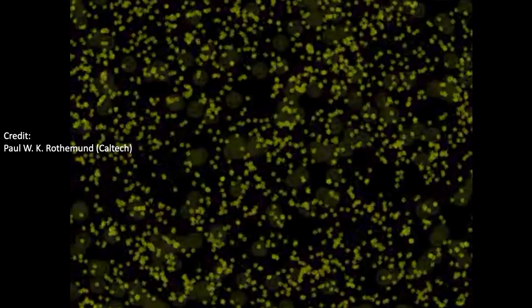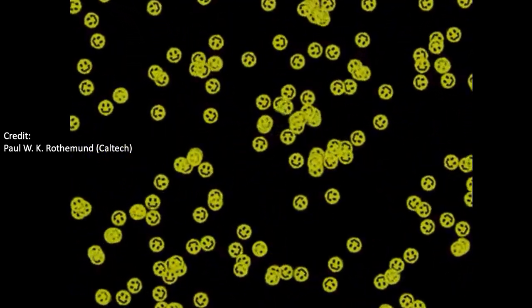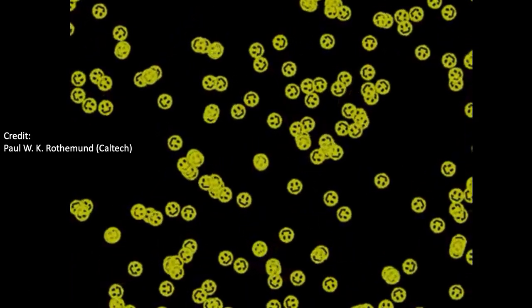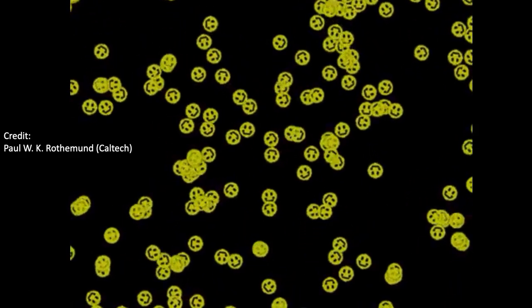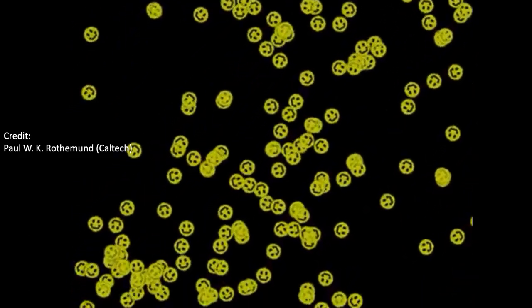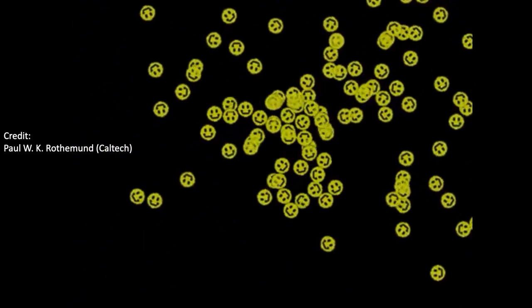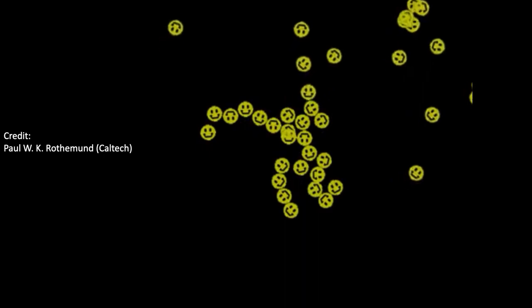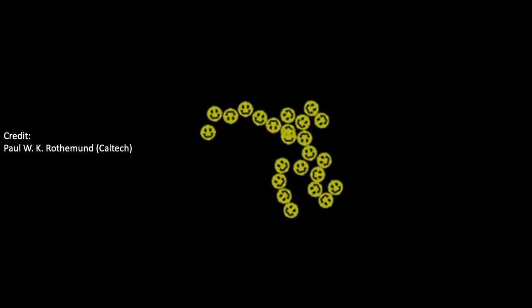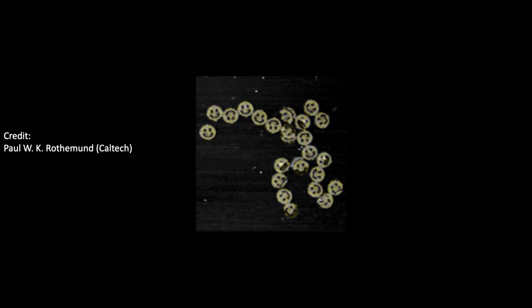What I meant by a parallel fashion is that many of these folded DNA nanoarchitectures can be obtained at once. Simply mixing the required DNA, heating it up, and cooling it down is enough to obtain many DNA origami. Herein, as an example, you're seeing the many smiley faces of DNA origami obtained in a single batch by putting them onto a substrate. Then, we can image them through an atomic force microscope. We can see the world's smallest happiness like this.